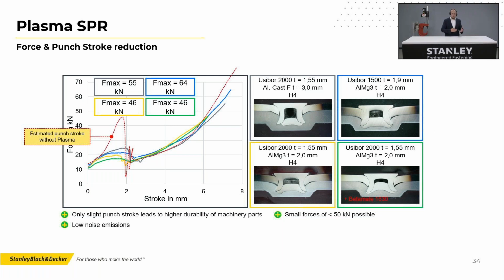And in addition to that, you have lower end forces, and you also have a much lower punch stroke. Usually, when you do that with traditional SPR, you need to punch through the ultra high strength steel, and you can hear it in the whole line. It can sometimes be really loud if you punch through these materials with an SPR.